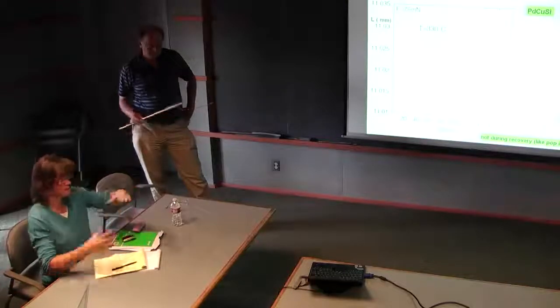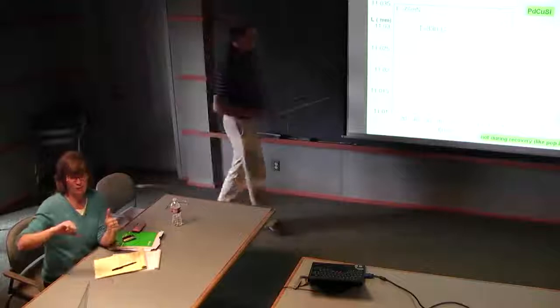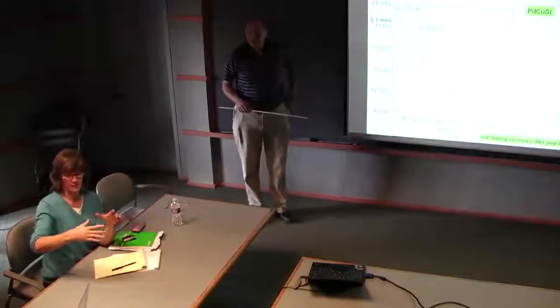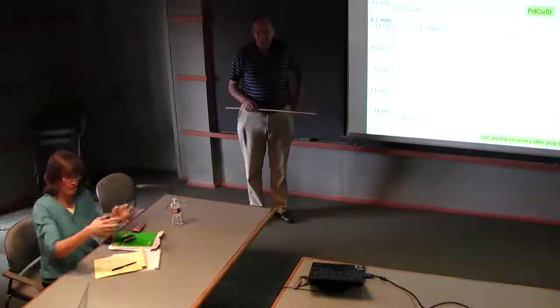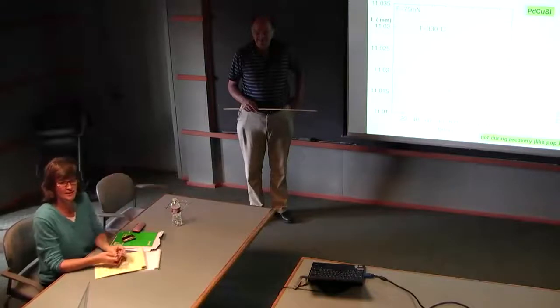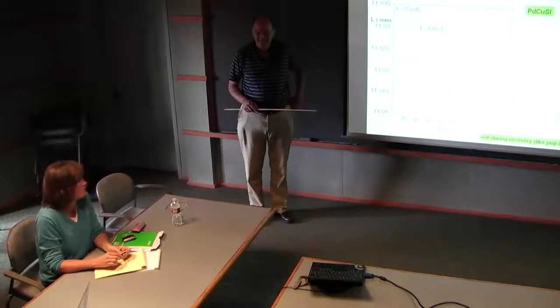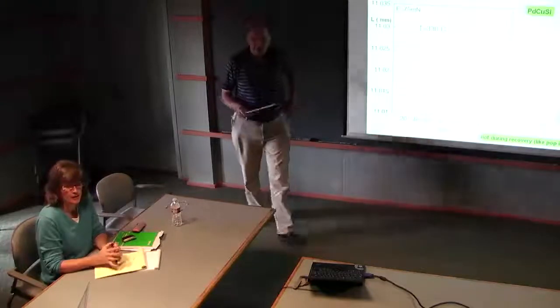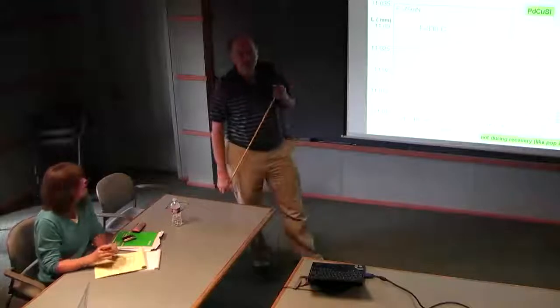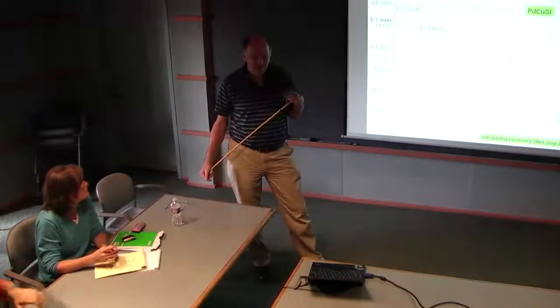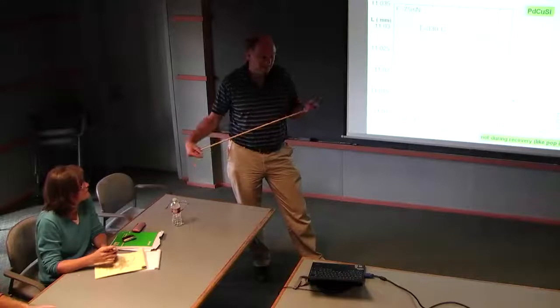There may be an argument to say that his waiting times are following the same scaling law. If you think, for example, about magnets with long-range forces, you could imagine that if you have a demagnetizing field and a large avalanche, you have to wait a long time because you just relaxed a lot of the field. You have to wait a long time till you trigger the next one. So this is not in the mean field model. Well, he's not talking about any model. He's just representing his results and saying that looking at the waiting times is interesting. We thought in the beginning there would be a Poisson distribution, and the results show it's not.